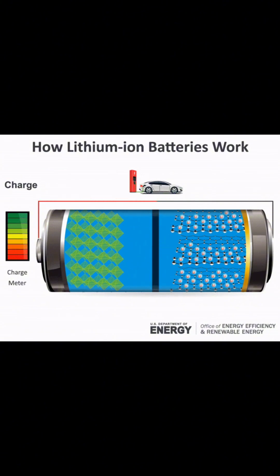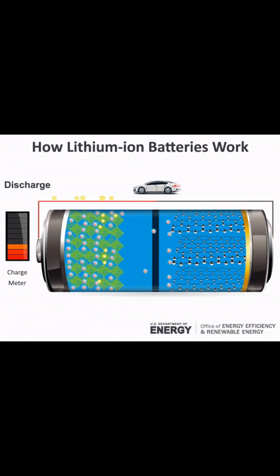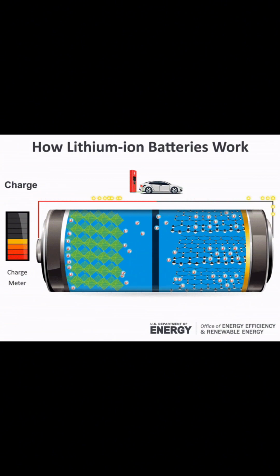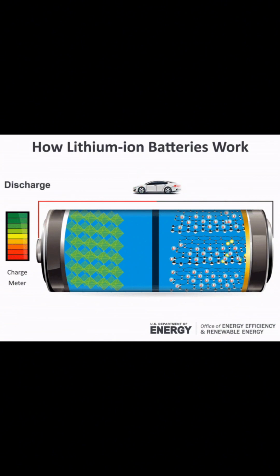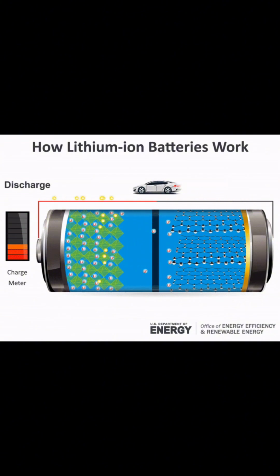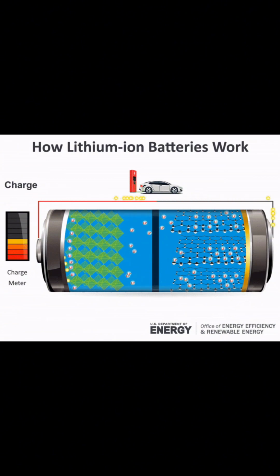Although many thousands of different materials have been investigated for use in lithium-ion batteries, the usable chemistry space for this technology that made it into commercial application is extremely small. All commercial Li-ion cells use intercalation compounds as active materials. The first one is the anode, or negative electrode, which is usually graphite, although silicon has often been mixed with graphite in commercial cells since 2015. Second, the solvents in commercial Li-ion batteries comprise organic carbonates such as ethylene carbonate and dimethyl carbonate that form a solid electrolyte interface on the anode, which allows for Li+ ion transport but not for electron transfer.